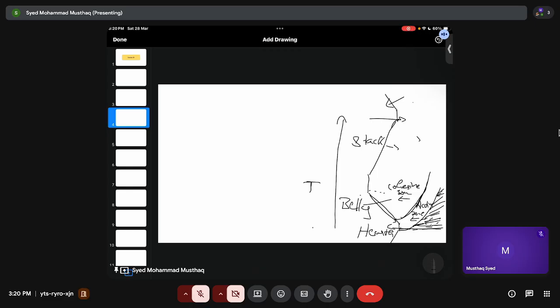So the top region is mostly your granular region, because the only thing you find there is reduction. That's all. There is nothing else. Now, why have these names been given? In the granular zone, you mostly have charging, drying, and preheating, because the gases coming from bottom to top have very high temperature, meaning the adiabatic flame temperature is large. So they pass their heat energy to the iron ore and coke layers coming from the top, okay?